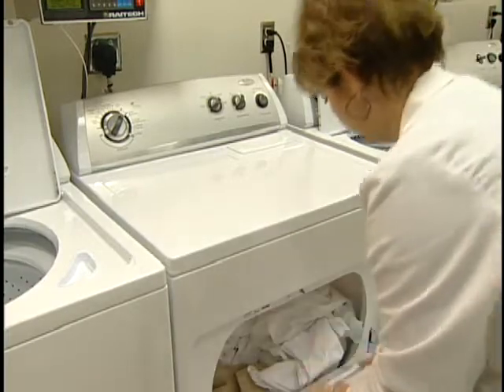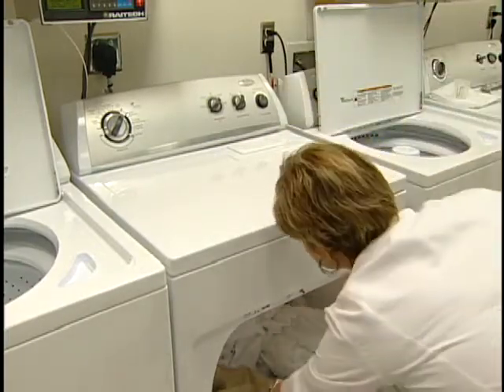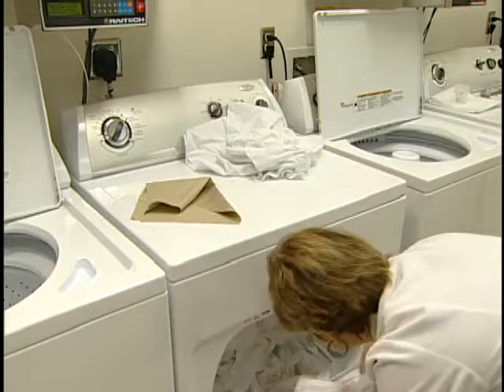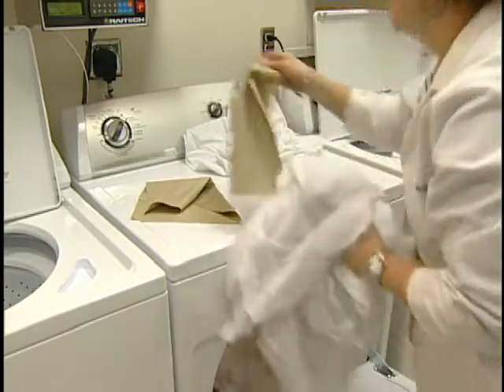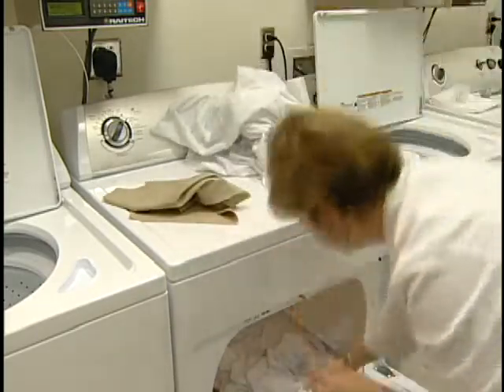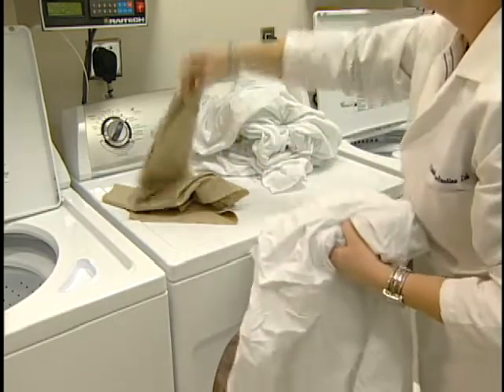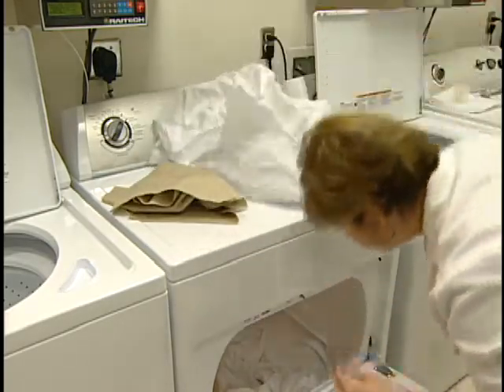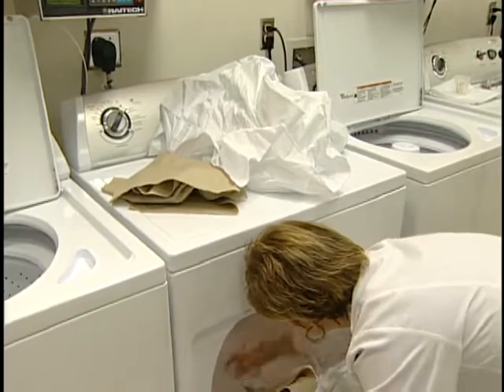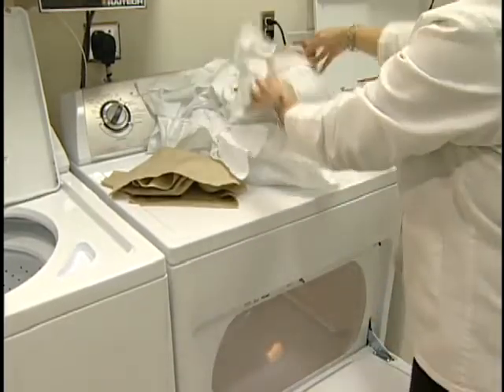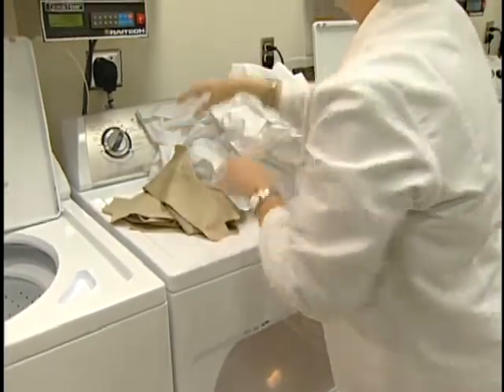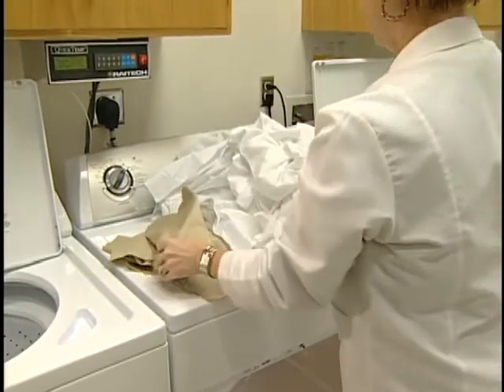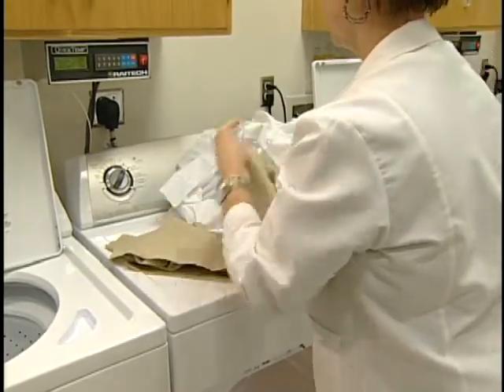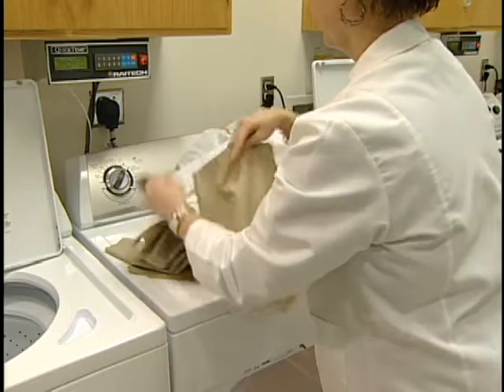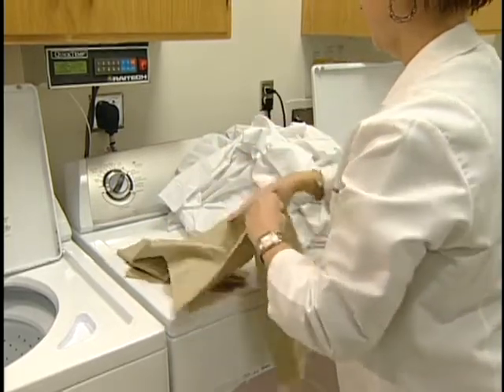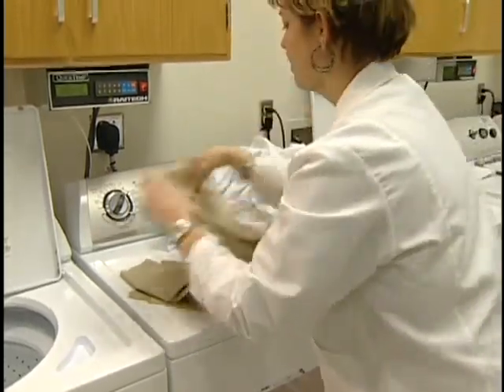If the specimens are to be tumble dried, allow washing to proceed automatically through the final spin cycle. Remove the test specimens immediately after spinning, separate tangled pieces, taking care to minimize distortion, and dry to the specified temperature. For fibers that are heat sensitive, lower temperatures consistent with producers' recommendations are required and must be reported. Operate the dryer until the total load is dry. Remove the load immediately after the machine stops. Overdrying must be avoided.